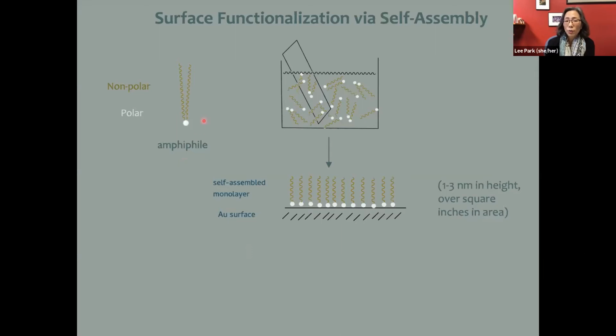So we can design molecules, or there are lots of examples of these molecules in nature, that are what we call amphiphilic. That is, they have both a polar group as well as a non-polar group in the same molecule. Okay, so you can prepare a molecule that's amphiphilic. And then what you can do is put that molecule in solution, and then we can dip a slide into that solution. And the slide is coated with a thin layer of gold. So you dip that slide into that solution for maybe 30 seconds or a minute, and you pull it out. And what you have is your glass slide with its thin gold coating.